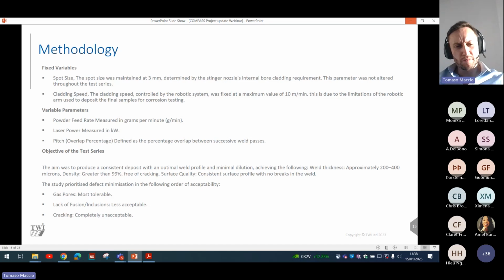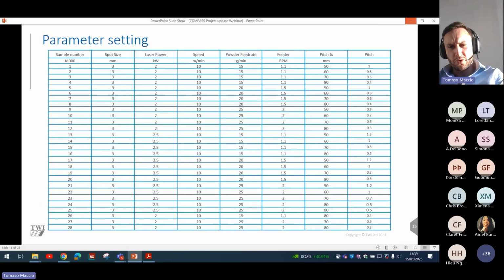What we did look at, though, to be similar towards the shafts is varying powder feed rate and laser power measured in kilowatts and pitch in overlap percentage. So we wanted to try and deposit as fast as possible so we could understand that we're working towards the end deliverable of understanding the economical benefits of utilizing extreme high-speed laser application. So for this, we completed a large full factorial parameter test series. So 28 samples for the first material, which was Inconel 625, and we're currently underway with doing the second material, which is stainless steel 316L.